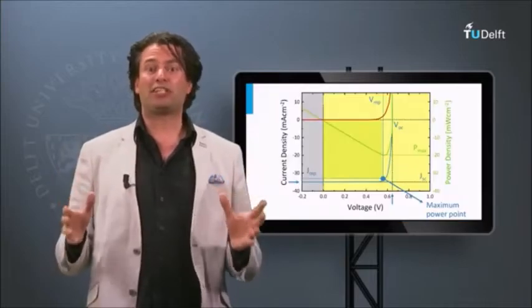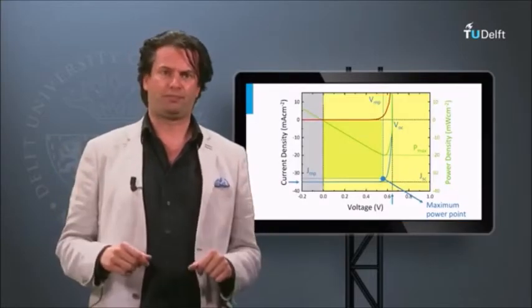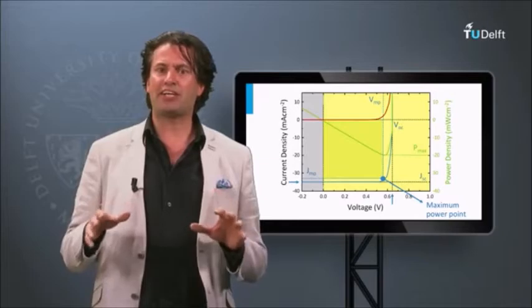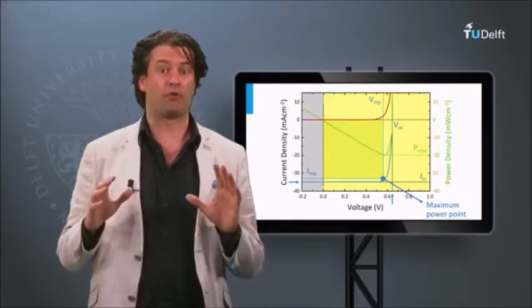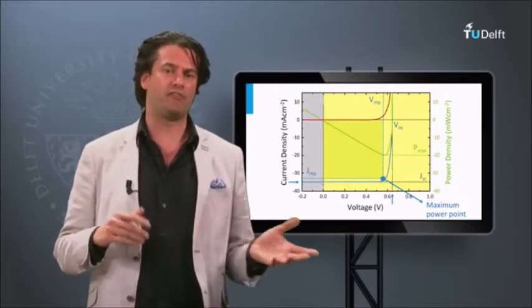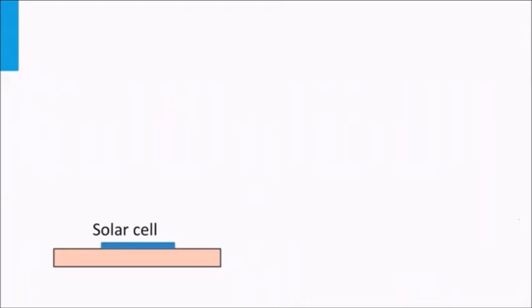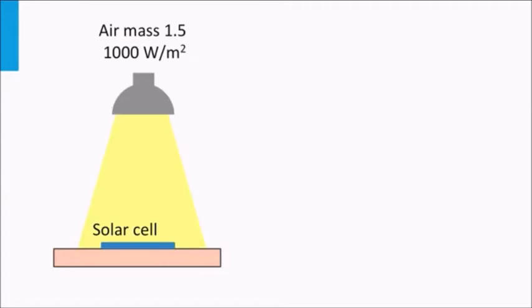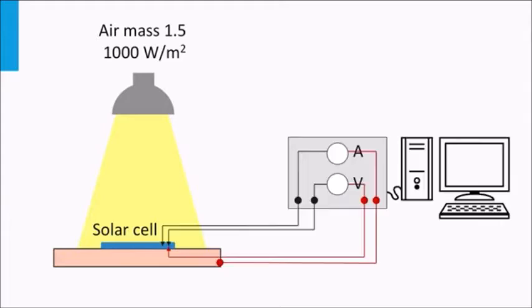We are going to measure the efficiency of a solar panel. We do this by measuring the JV curve and its external parameters as discussed in the previous block. How does such experimental setup look like? It consists of several components. The first component is a solar simulator, which is a light source that simulates both the shape of the AM 1.5 solar spectrum and an irradiance of 1000 watts per square meters.